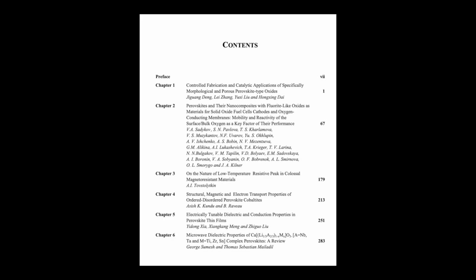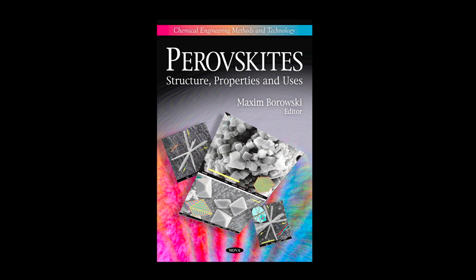Wow. This huge boost is now widely attributed to the creation of atomic superhighways at the interfaces. The lattice mismatch and the resulting strain, plus the tendency for charge redistribution, space charge effects, at the perovskite-fluorite interfaces, create regions of high disorder and significantly enhanced vacancy concentration right at the boundary between the two materials. Oxygen transport is then dramatically accelerated along these interfaces, effectively bypassing the potentially slower diffusion pathway through the bulk of either material.